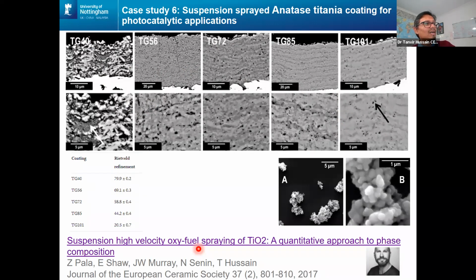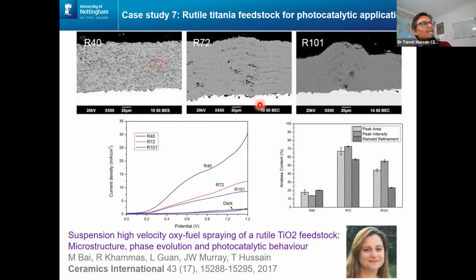That was our very early days of work on suspension, but it taught us that by optimizing the spray window, you could come up with very different types of microstructure and different phase content. Moving on from anatase to rutile, we are still talking about titania, but this time we are using a rutile suspension sprayed at 40 kilowatt, 72 and 101. And as we see, the anatase content changes quite significantly depending on the flame power, but it's not a linear change.